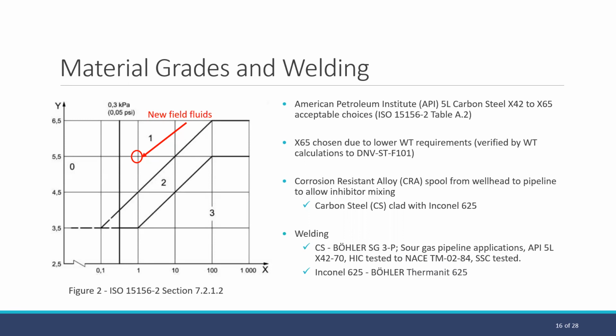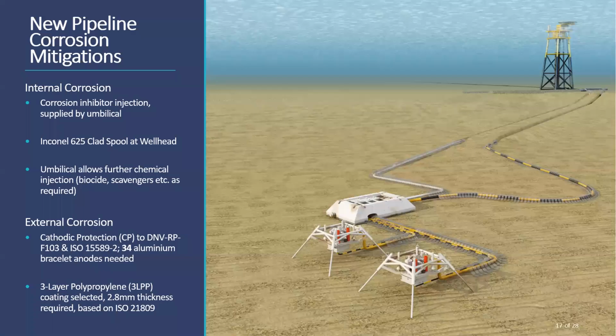We're also choosing a CRA spool at the inlet. This will help allow for corrosion inhibitor mixing and also reduce the worst case corrosion rates at the inlet. Because we've got high temperature, high chlorides, and some H2S, we can't choose things like 316L. We did think about a solid duplex, however, given the requirements for external corrosion protection, for cathodic protection, we decided not to because of the cracking risk. So we've chosen Inconel 625 because the spool is only going to be of short length. For welding consumables, we've been to specific manufacturers and suppliers, and we picked out 2 consumables we think would be perfect, for both carbon steel and Inconel 625 if welding is required.